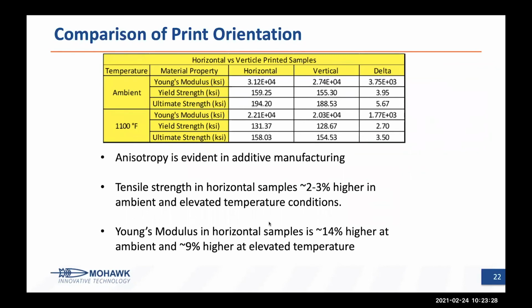when I talked earlier about anisotropy, are the properties the same regardless of how it was laid up? We see some evidence that there is a minor variation in the two axes. So if you look at the horizontal specimens in the first white column, and then the vertical specimens in the second column, you can see there are some differences here. It turns out there is some anisotropy evident. Again, not substantial. It's only maybe 2 to 3% in the tensile strength, where the horizontal or longitudinal specimens do show higher properties at both ambient and elevated.